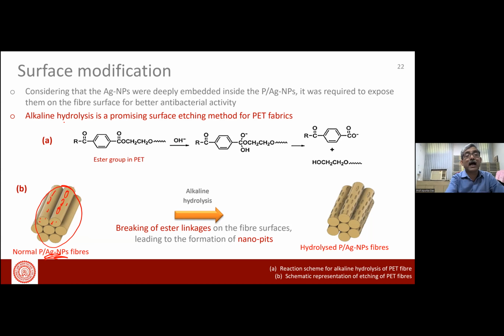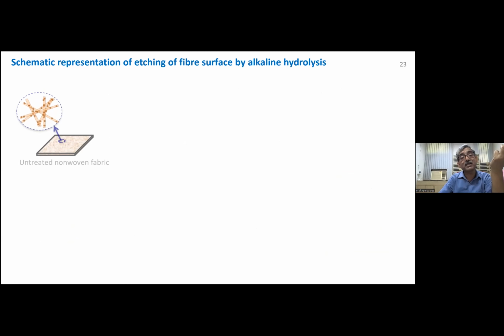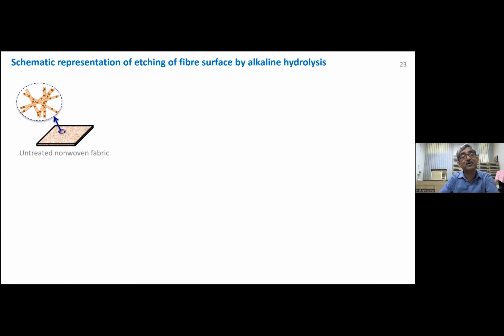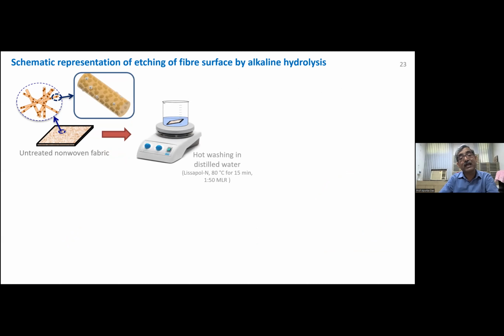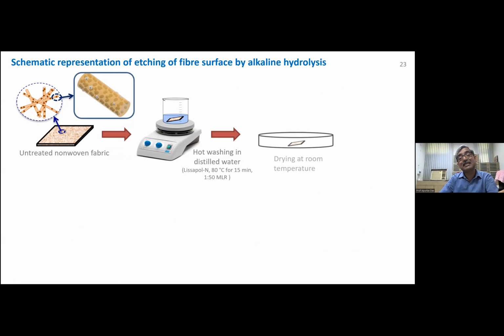So what we have done, we have used the alkaline hydrolysis process. You can see the hydrolyzed nanoparticle, it is exposed, and which is active for the killing of bacteria. Now the process is here. You can see the untreated non-woven fabric, and then we have treated the non-woven fabric. So this is the untreated, and then we have hydrolyzed. So different stages are there.